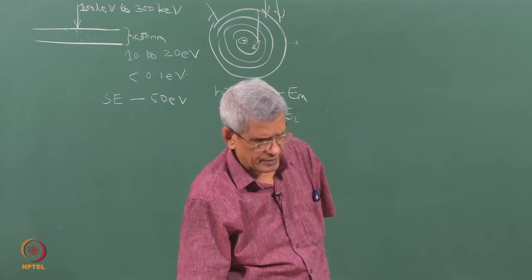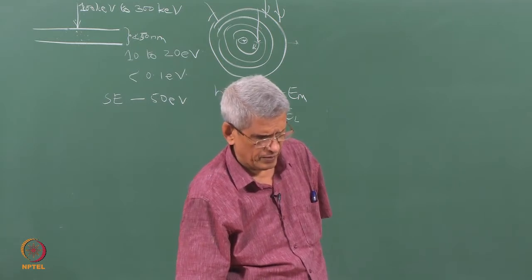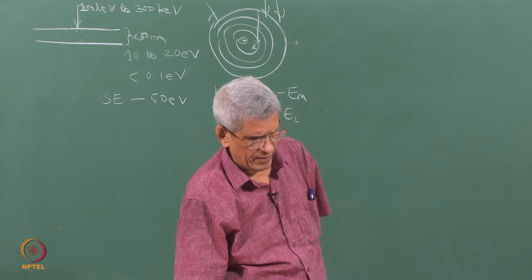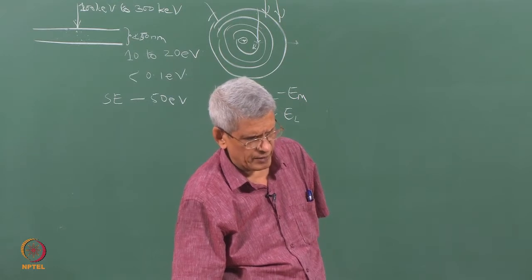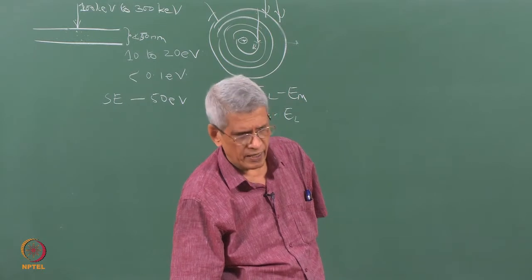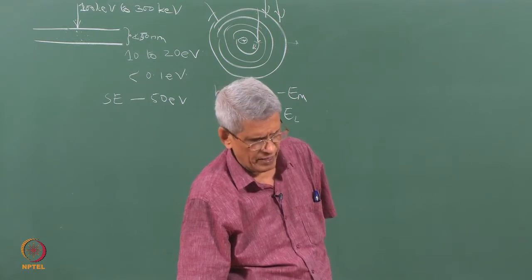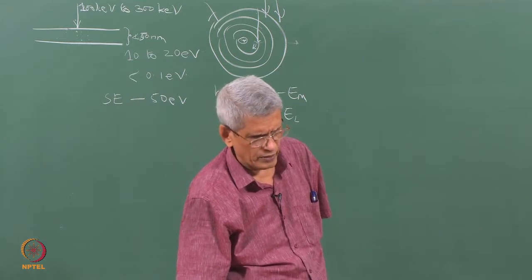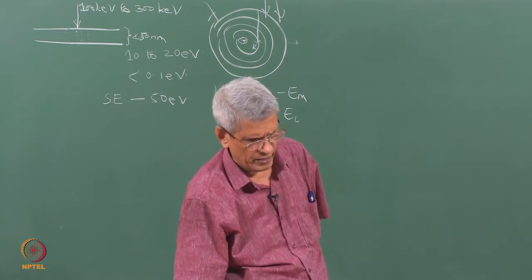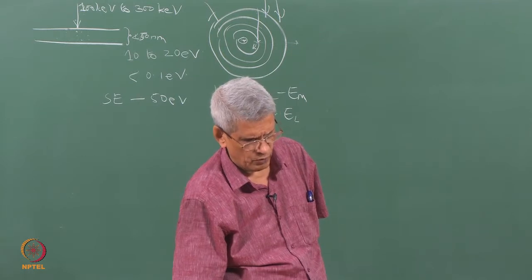When the X-ray with this energy comes out of the sample surface, this characteristic X-ray we can measure it, counting the number of X-rays with this energy coming out, we can find out the concentration of that element in the sample. This way we can find out the composition of the sample. This technique is used in SEM, in electron probe microanalysis,